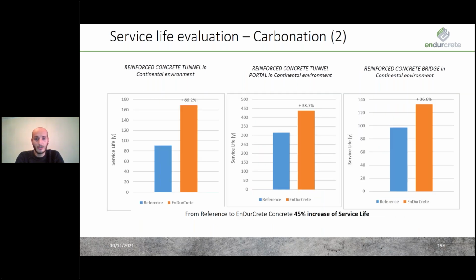In this case, for the carbonation, we can see here that a huge increase in service life can be reached by using the EnDurCrete cement instead of the reference one. And on average, we can reach a 45% increase in service life. So we can see that the use of EnDurCrete and also the implementation of the nanoclay inhibitors can lead to a very high increase in service life.